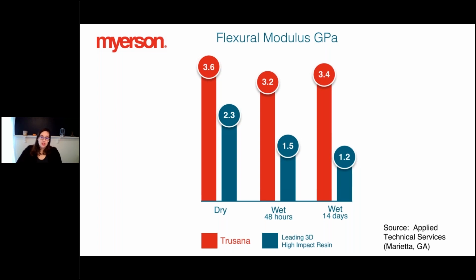Now, the next thing we did in our testing was to submerge these parts of Trusana in water for 48 hours, still outperforming the competitor. Then we took it a step further and submerged these parts for 14 days in water. And still, not only is Trusana pretty consistent with a flexural modulus remaining around 3.4 to 3.6 gigapascals, but the competitor leading 3D high impact resin actually decreases in flexural modulus as you increase that exposure to water. So this is something we're really proud of and is really a function of the chemistry and how it functions.